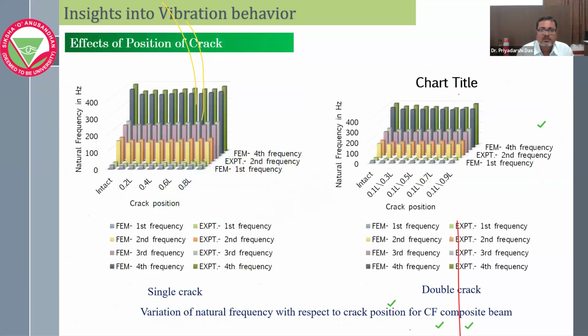Now this is the effect of the position of the crack. The position of the crack, that means L1, L2, L3, we have taken for the intact beam at 0.2 L, at 0.4 L, at 0.6 L, and 0.8 L. What cracks have been formed? Now, if I take the single crack position, we can find at which position the crack exhibits the lower frequency or maximum drop. That means from the intact, at which position the crack exhibits the maximum drop.